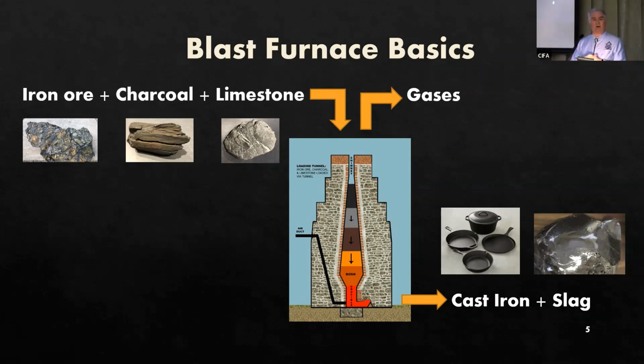The charcoal was the fuel, and it burned primarily at the bottom of the furnace where air was injected into the furnace. The gases from the burning charcoal and also from the limestone and ore went up the stack and exited out of the top. As the solid limestone and iron ore descended deeper into the furnace, they eventually melted. And then the iron was tapped or discharged at the bottom of the furnace, where the slag was also removed from the furnace.